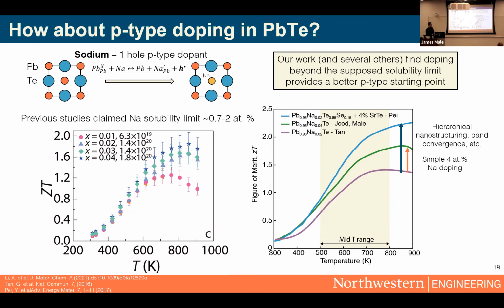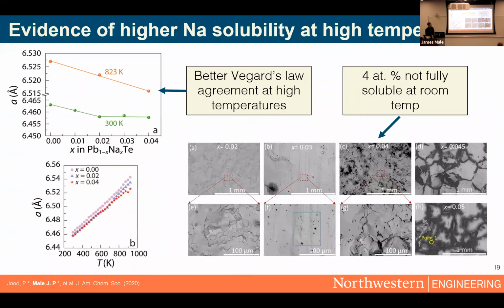But what we have been seeing recently in both our work and in other studies is that doping beyond this 2% level actually gives you a pretty good enhancement in ZT. What that means practically is if you did all those extra band engineering and other thermoelectric engineering strategies on this newer 4% doped composition, you could potentially push the performance even higher. So we want to understand why this higher sodium concentration was improving performance.